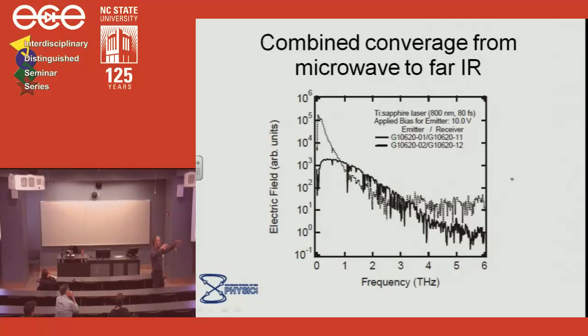Now, the other thing you might say, well, why don't you put a hemispherical on the bottom and use a confocal geometry? It turns out, and this was figured out by a very smart Russian about 40 years ago, that the confocal geometry is more sensitive to imperfections in the construction. And so it turns out that the hemispherical resonator gives you very low diffraction losses, and it's relatively insensitive to imperfections in construction.